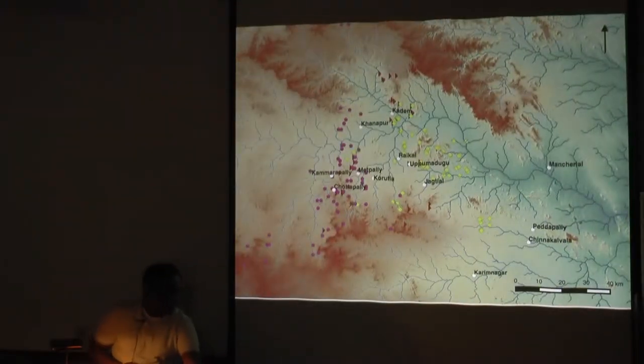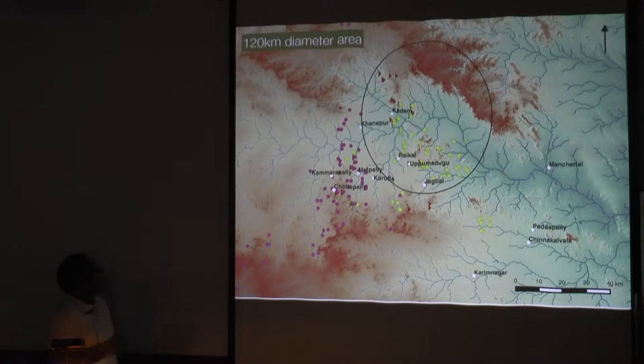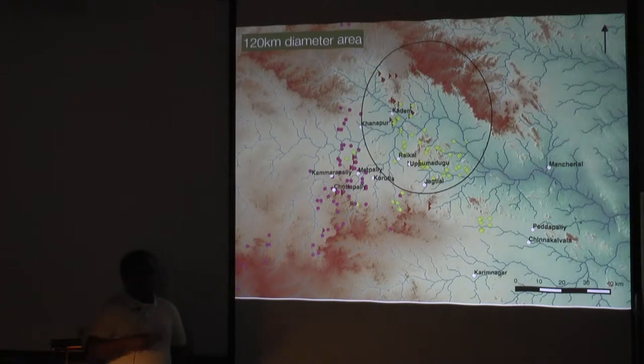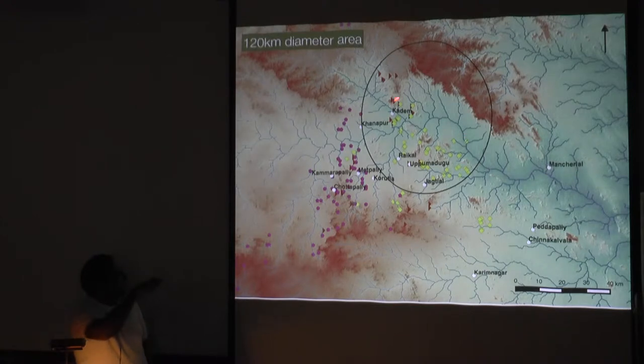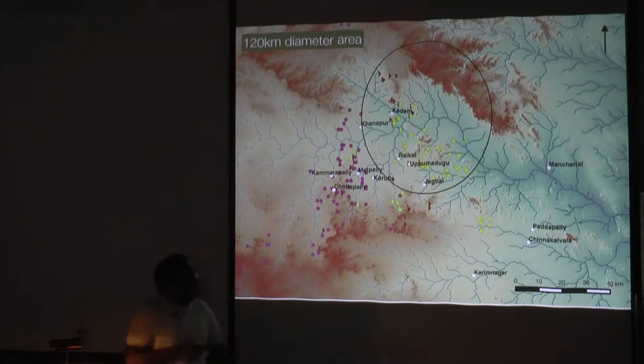So basically we surveyed at that time an area of 120 kilometer diameter where this circle is. The pink dots here are the places that Thelma had surveyed earlier, and also Dr. Jaikishan had surveyed earlier. So the pink dots represent the steel making and laterite smelting area, but we surveyed the magnetite smelting area from here, and there is hardly any evidence of steel making in the magnetite smelting region. And the red triangles are the sites that I added later during my PhD field work.